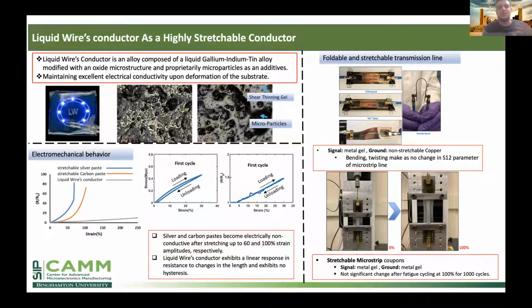One of the applications for this is a foldable and stretchable transmission line in RF applications. As you can see, for the foldable and bendable transmission line, the signal line is a metal gel and the ground plane is copper. For stretching, both the ground and signal are liquid metal. After subjecting it to 100% strain for 1,000 cycles, the S12 parameters before and after are mostly the same, so no significant change after cycling at 100% for 1,000 cycles. Thank you all for your attention.